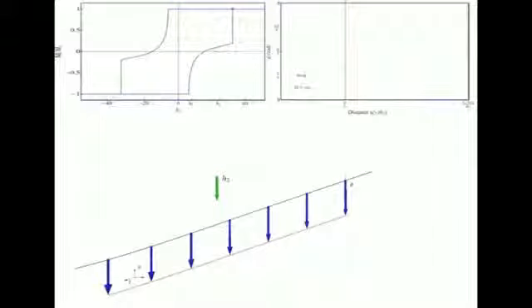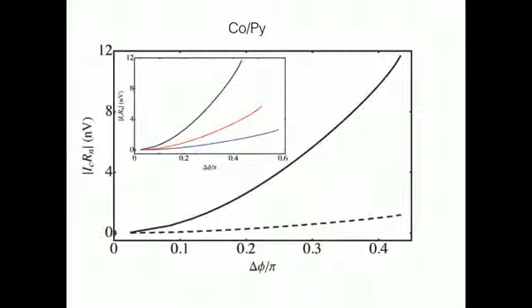Applying an external magnetic field induces a partial domain wall, which may be wound up or down until the field is sufficiently large to return to the homogeneous configuration but in the opposite direction.